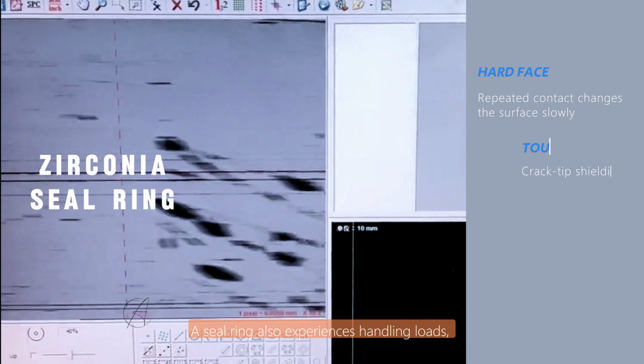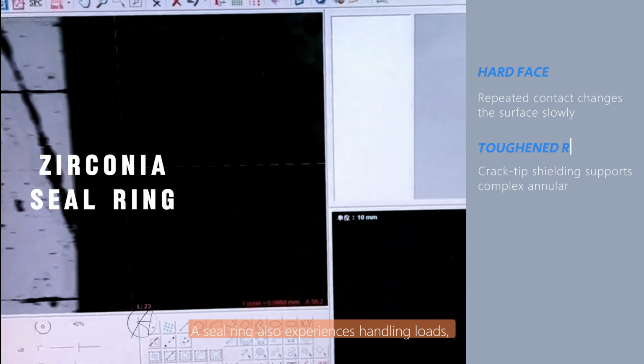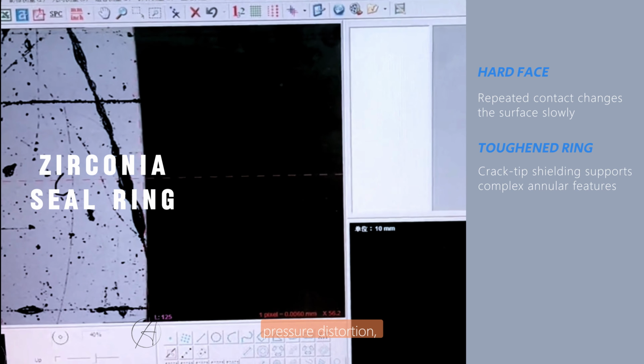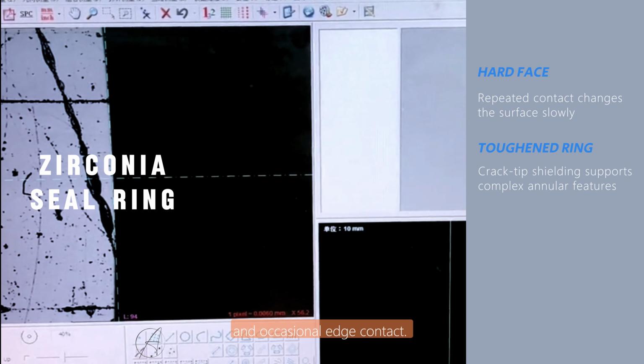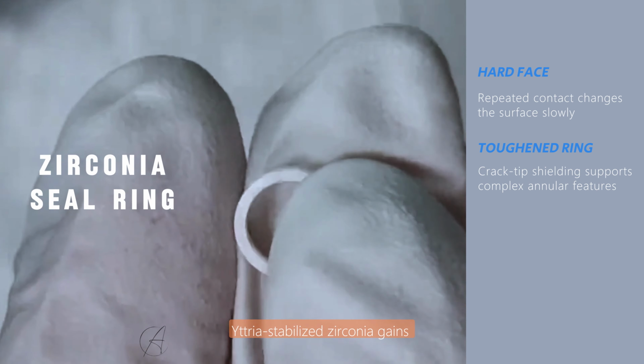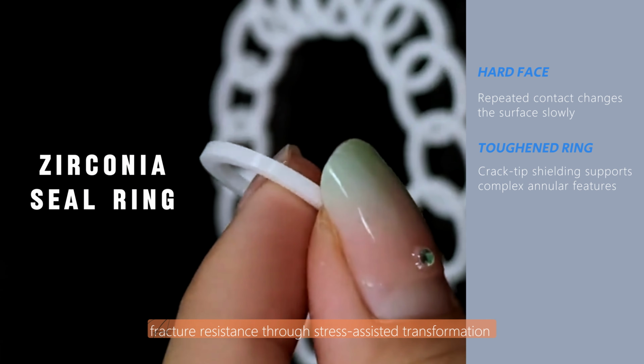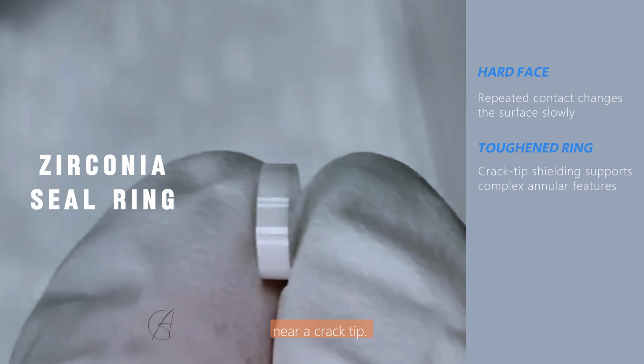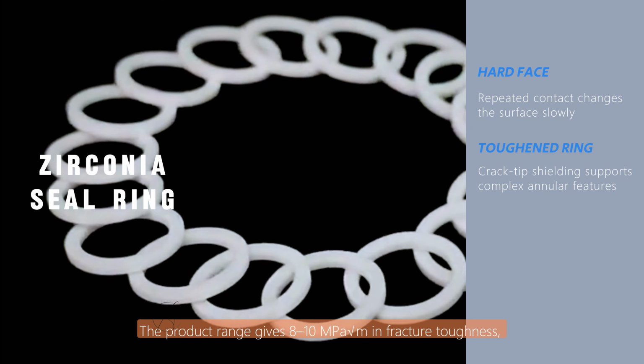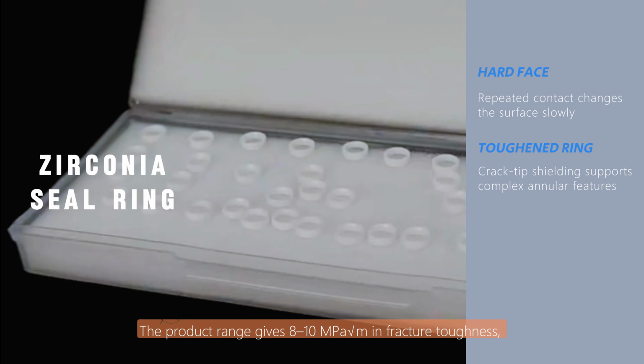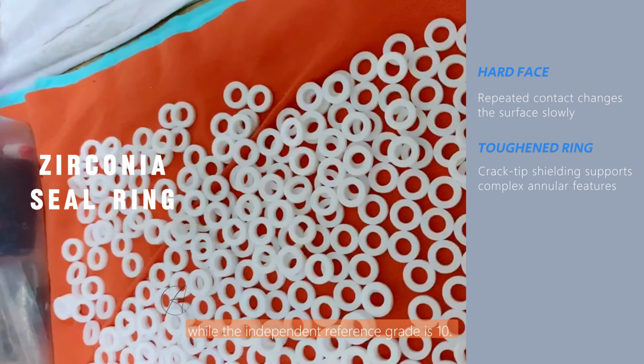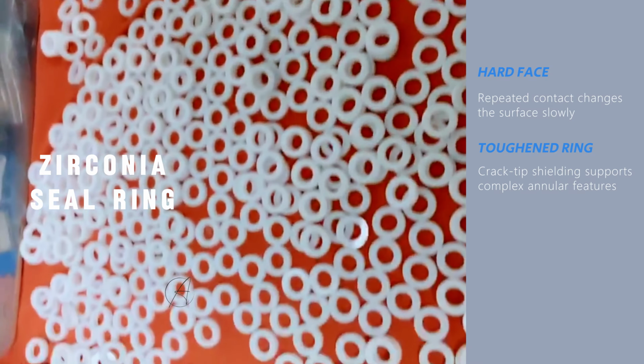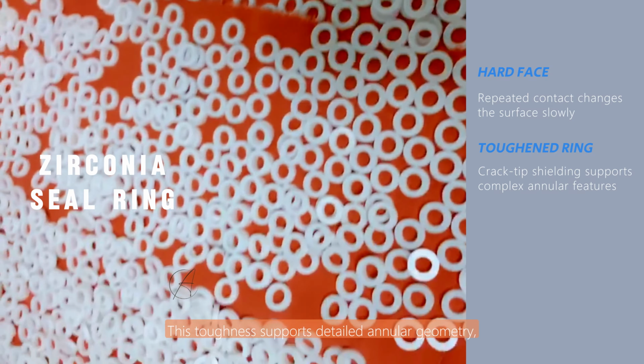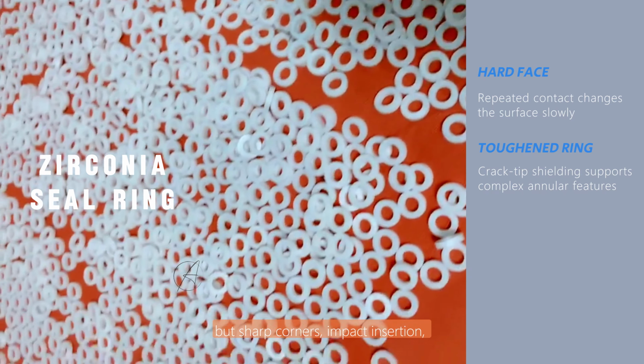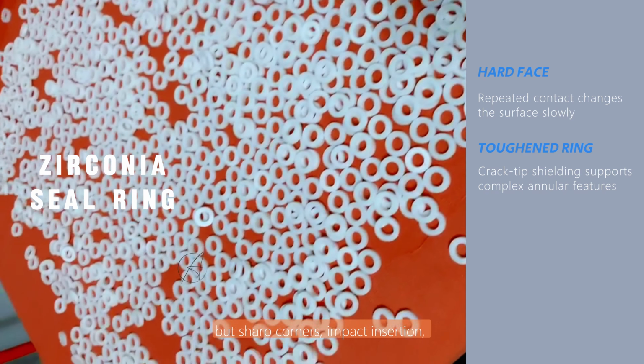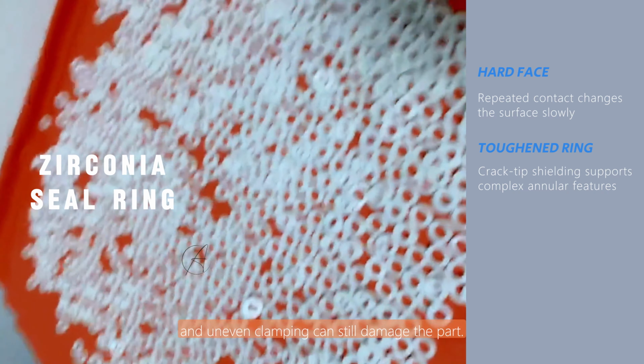A seal ring also experiences handling loads, assembly stress, pressure distortion, and occasional edge contact. Yttrium-stabilized zirconia gains fracture resistance through stress-assisted transformation near a crack tip. The product range gives 8 to 10 megapascal root meters in fracture toughness, while the independent reference grade is 10. This toughness supports detailed annular geometry, but sharp corners, impact insertion, and uneven clamping can still damage the part.